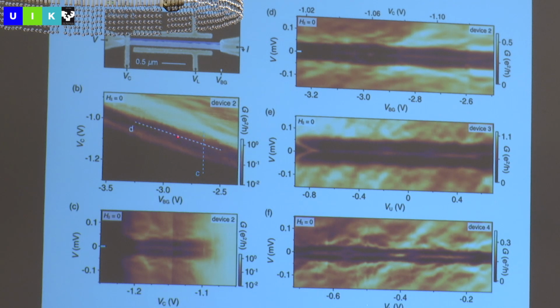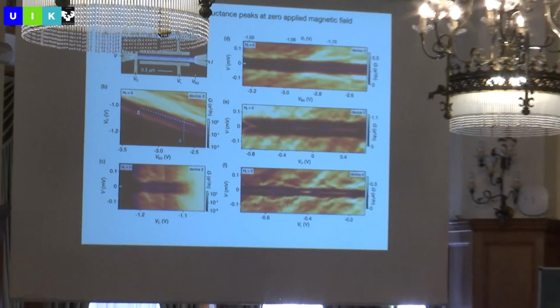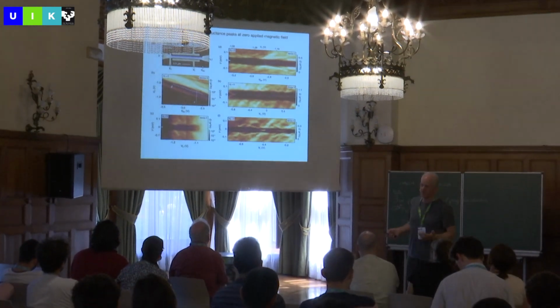And when we change the back gate along either the upper gate or the lower gate, what you can see is, and I want to emphasize, this is zero magnetic field. This is after we've swept up the magnetic field, come back to zero, and there's no external magnetic field now. The wire thinks it's in a Tesla and a half, but there's no applied magnetic field. And it doesn't think it's in a Tesla and a half because of the magnetic field from the ferromagnetic material. There is no magnetic field from the ferromagnetic material except at the very ends where it comes out. It's just scattering off of the ferromagnet. And what you can see is it makes a zero bias peak.